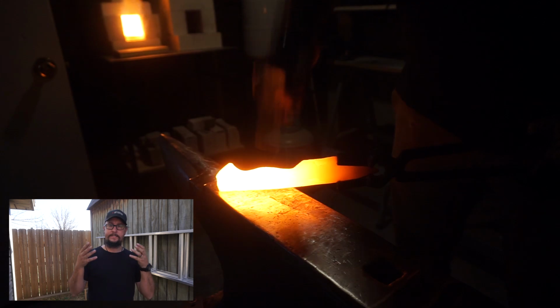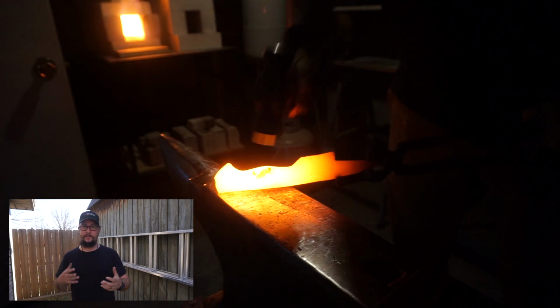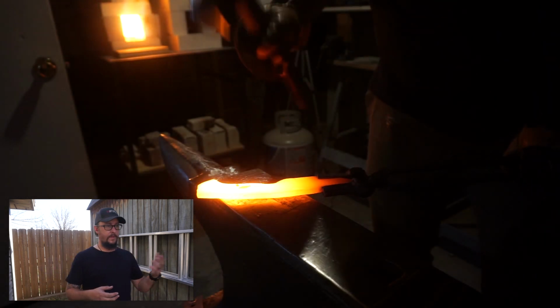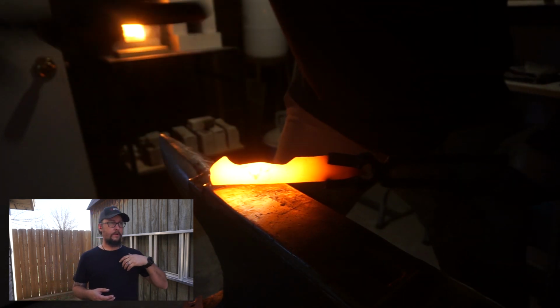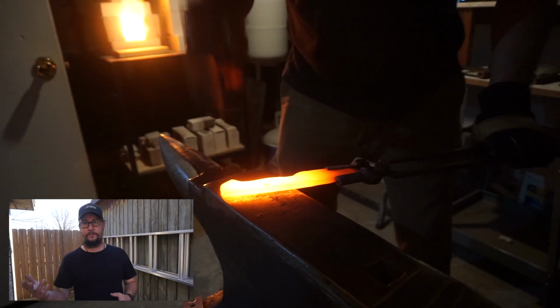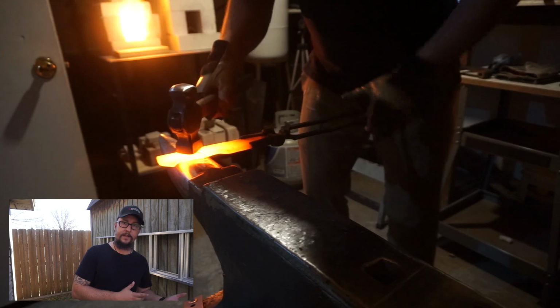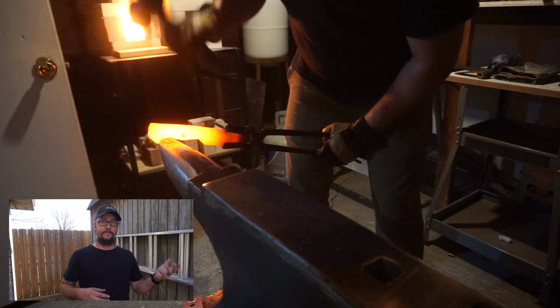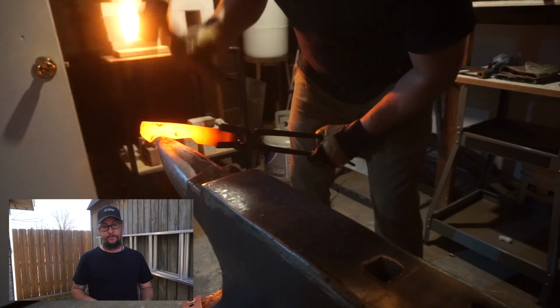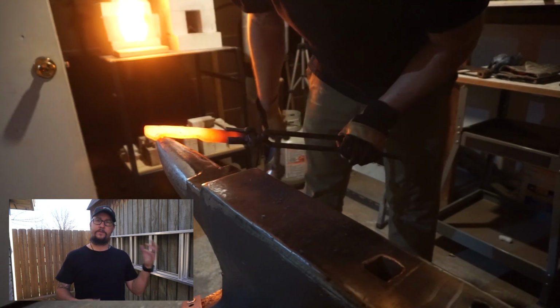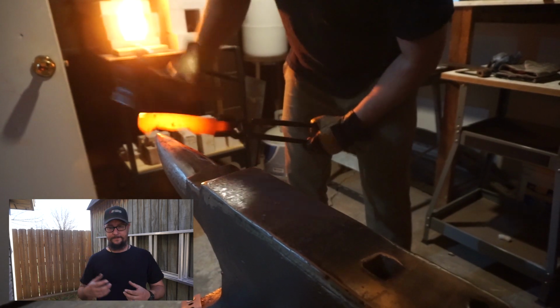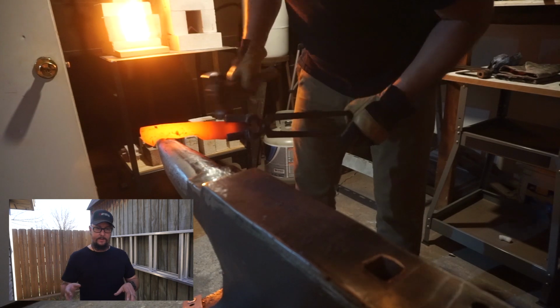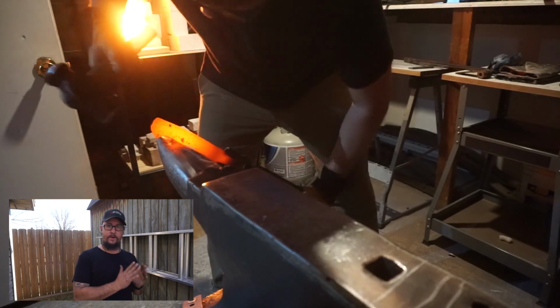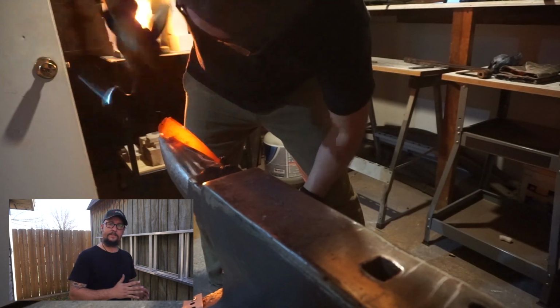Now, when it comes to tempering, you've got a lot of people that have different processes for that. You've got people that temper at 375 or 400 degrees for 2 hours. You've got people that do 375 degrees for an hour. You've got people who do 400 degrees for an hour. You've got people who do all kinds of different temperatures and different times based on how they like their hardness to be at the end of their process.